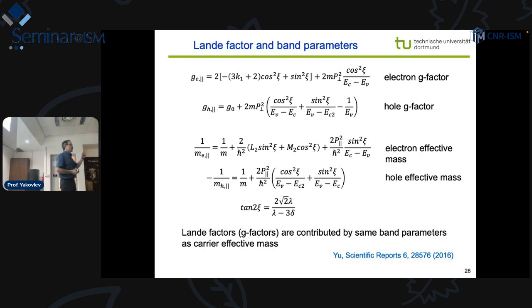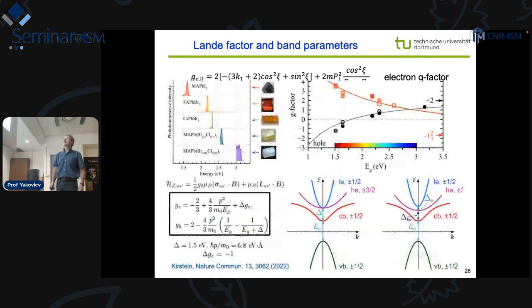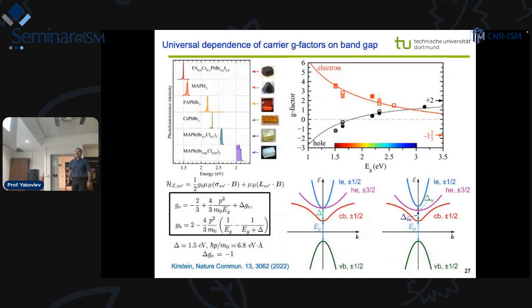So in fact, if we measure g-factors, their anisotropy, their values, we can get information about the effective masses. And this is especially important for the perovskites, where the mobility is low, and measuring effective masses by cyclotron resonance, for example, doesn't work. So it's still an open question how to do it. So here we can get valuable information.